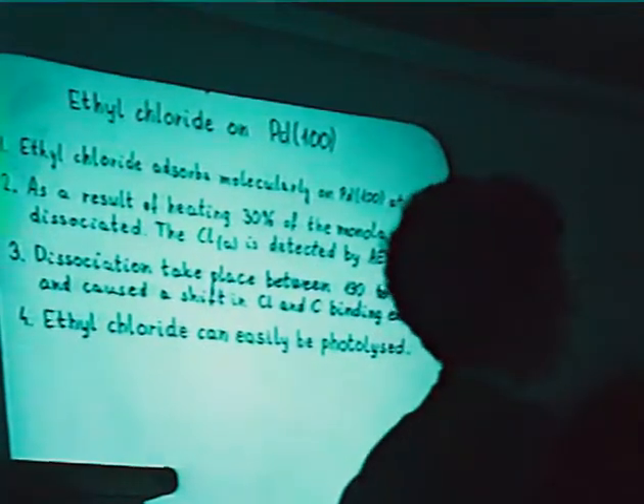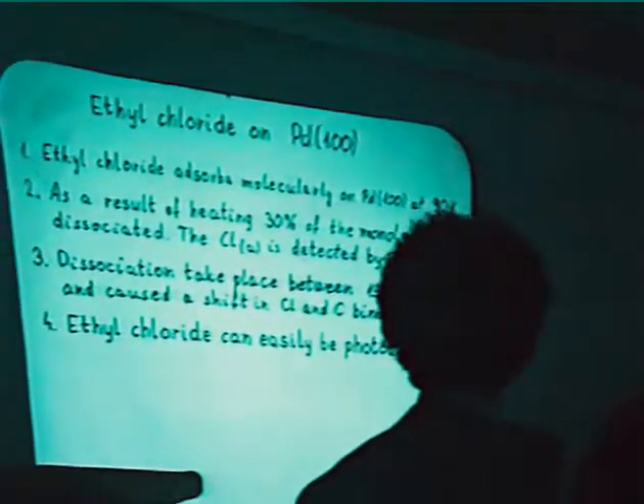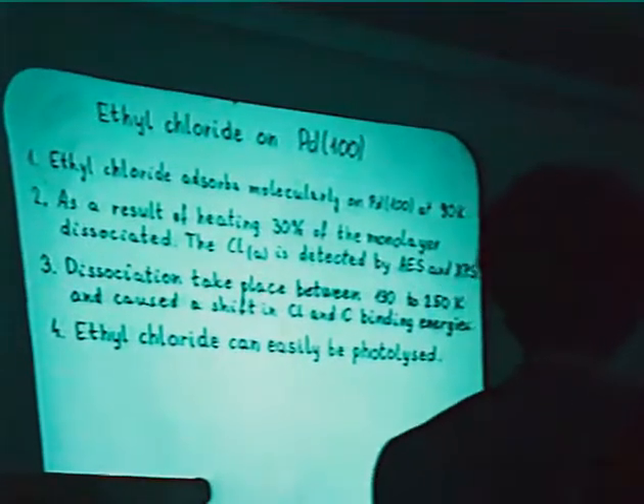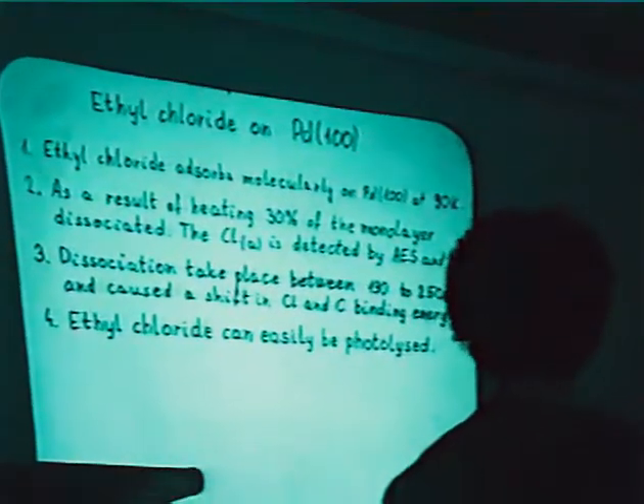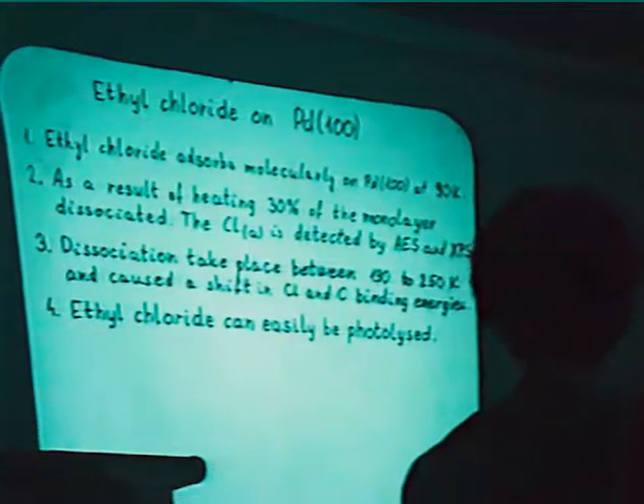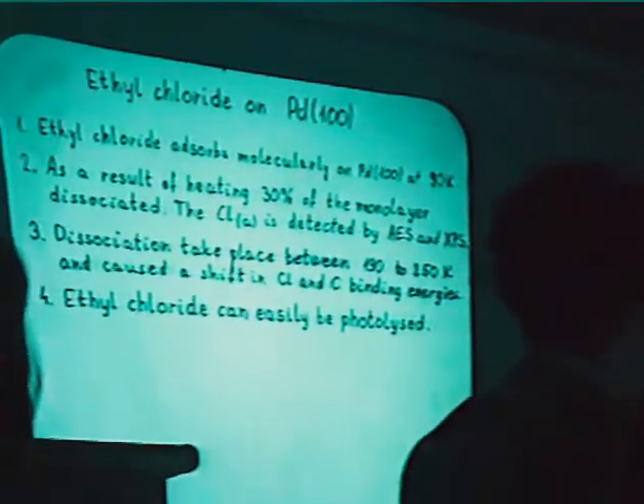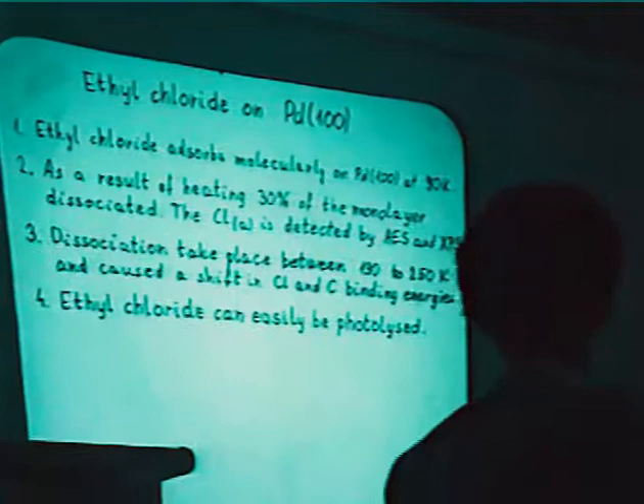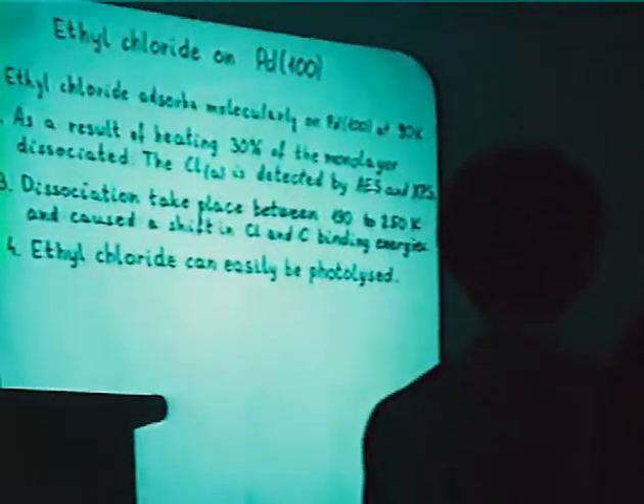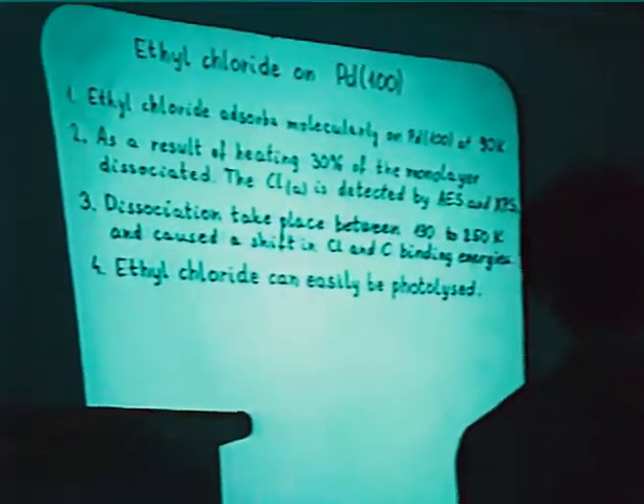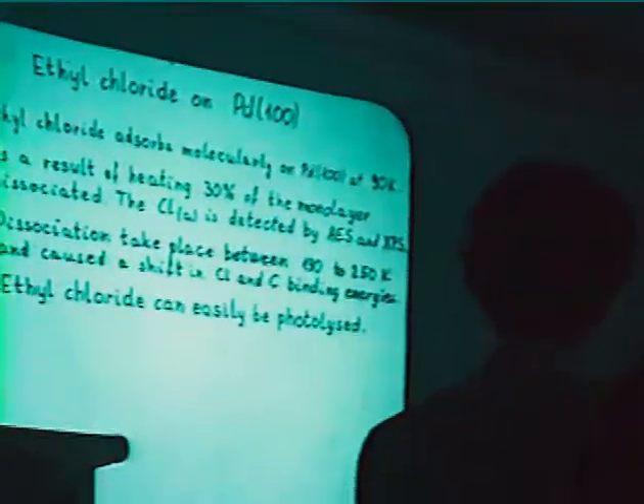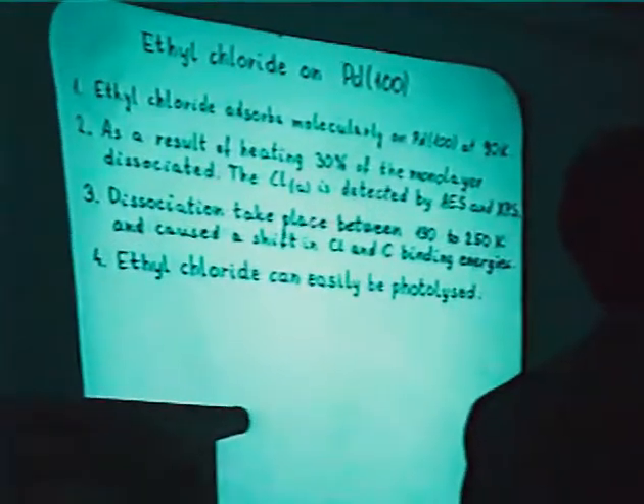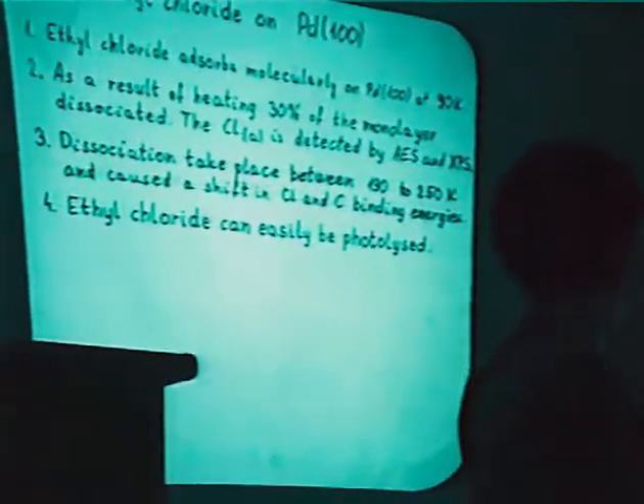about one third of the monolayer dissociated. Dissociation takes place between 190 and 270 K. It caused a large shift in XPS. And the ethyl chloride can easily be photolyzed. Let's see the evidence.